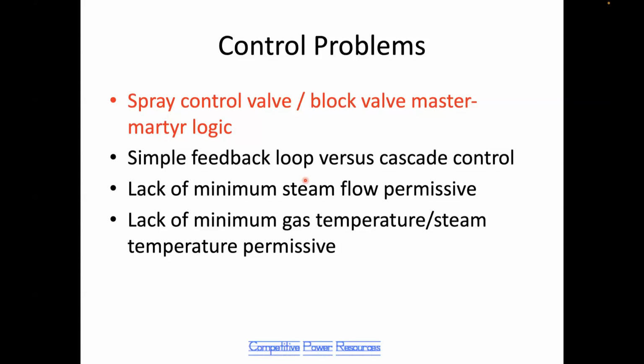Most designers want to prevent the control valve from leaking because it's a very expensive valve to repair. If you do that, the control valve will open first so that it has no differential pressure across it. Then the block valve will open and take all the damage. It's being martyred to take the damage in order to protect the control valve. When you do that, after very few startups, the block valve is now leaking through. And now forevermore, the control valve actually has differential pressure across it because the block valve can no longer protect it. Then the control valve becomes damaged. They're both leaking at this point, and that causes the leaking that we saw in the data that then damages the pipework.